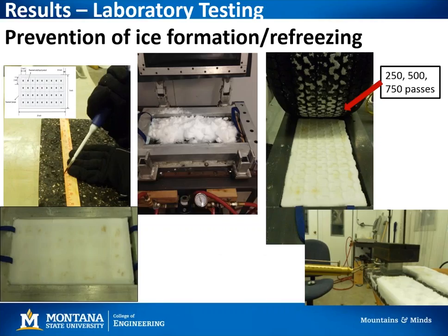So we also wanted to look at how these products prevent ice formation or refreezing, and this was actually measured using the friction coefficient. So we used a similar method to prepare the samples. We put the product on the asphalt, we made the snow, we compacted it, and then we trafficked it. And while this looks very similar to the shear force or shear strength, it's actually measuring friction. And we'll just get into the data.